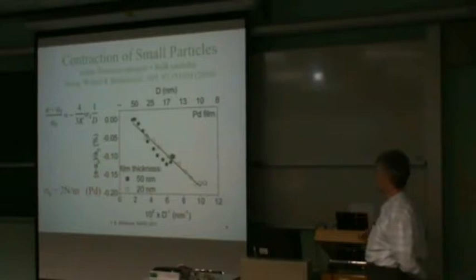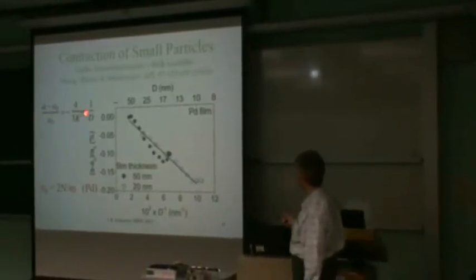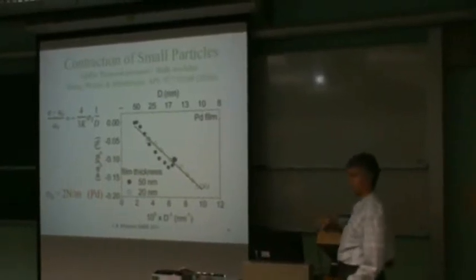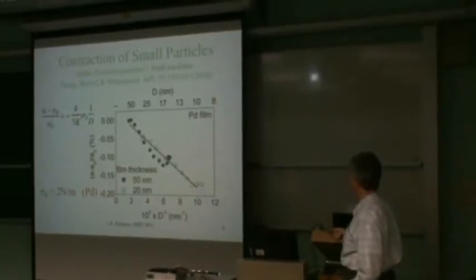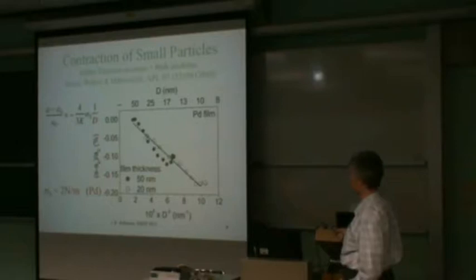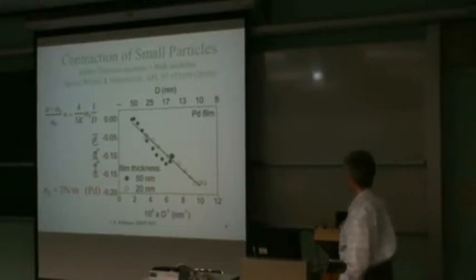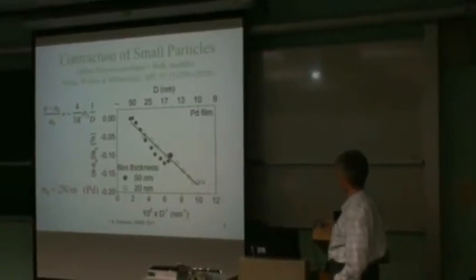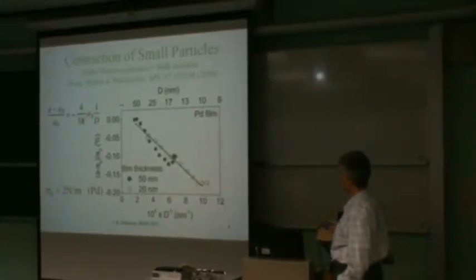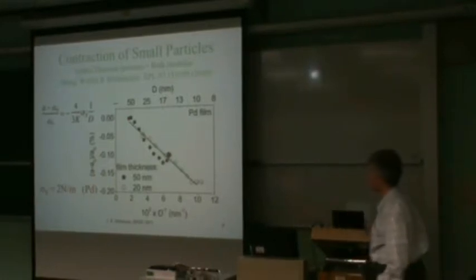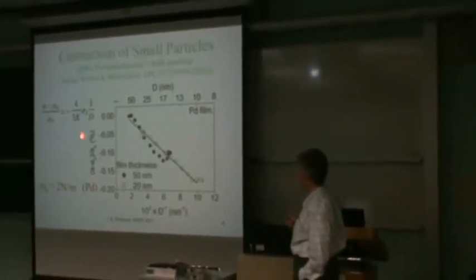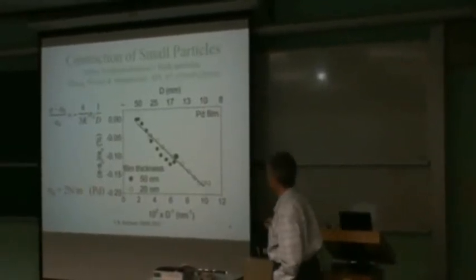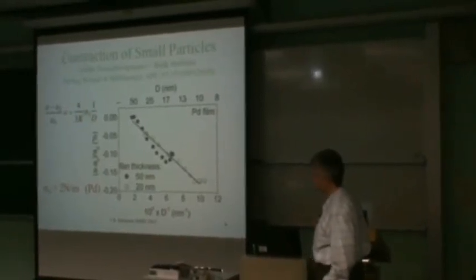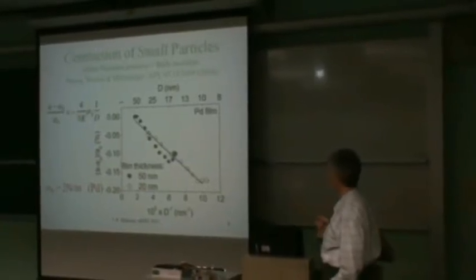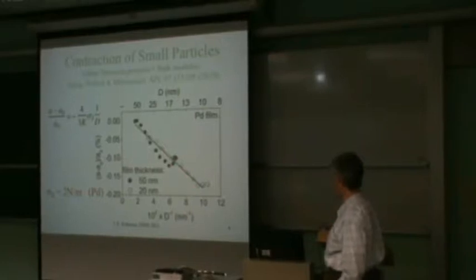And what you find is a linear behavior, and the linear behavior can be understood fairly well. In this case, the particles are assumed to be spherical, and a spherical particle with a surface stress on it, which is represented by this symbol here, will have a pressure difference across it due to the fact that it's got a curved surface. And the pressure difference is equal to the stress divided by the radius, so it can be converted into the diameter. And the response in the lattice constant with a couple of geometric factors is just given by the bulk modulus. So the only symbols that appear in this equation that gives the straight line that fits the data, which is the linear relationship with 1 over the size of the particles, contain a measure of the surface stress, which turns out to be 2 newtons per meter, which is a typical number for a surface stress, and the known bulk modulus of the material, and that gives a good straight line.